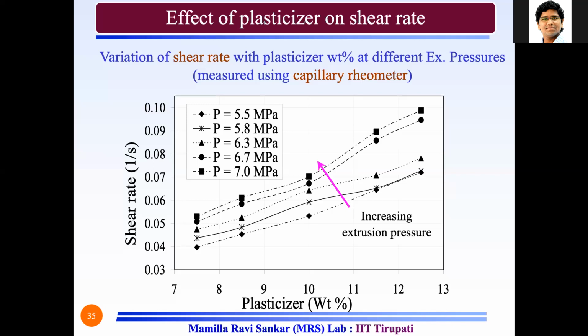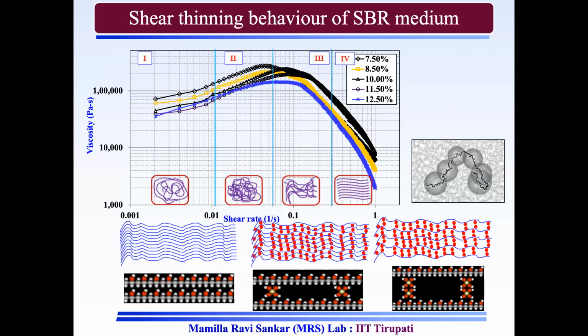So my shear rates are in the range of 0.04. Assume that for the safe side, it is 0.03 to 0.1 or 0.11. This is the range of shear rates. Now, once I know the shear rates, I am going to put those shear rates and I am giving some tolerances on both sides, and I am measuring the rheological properties.